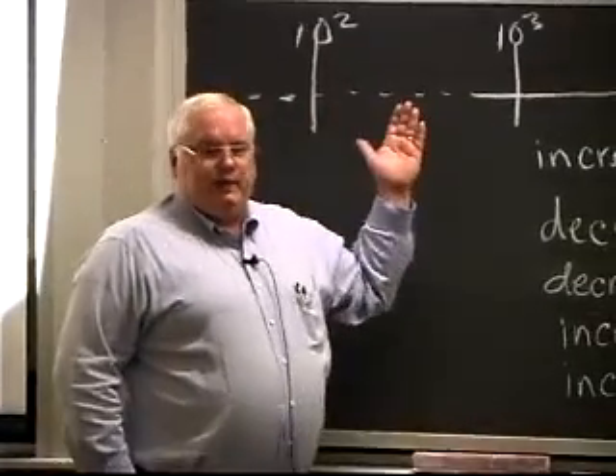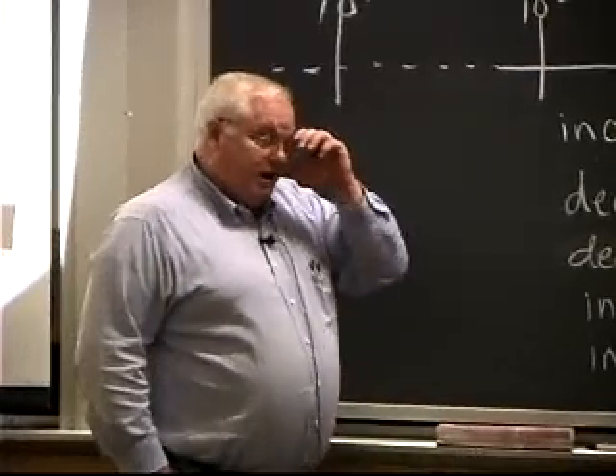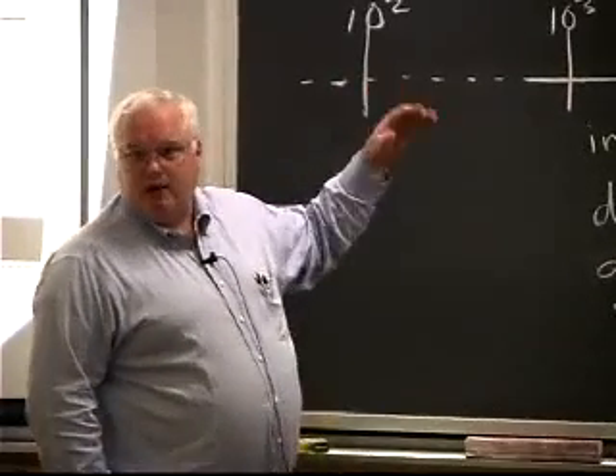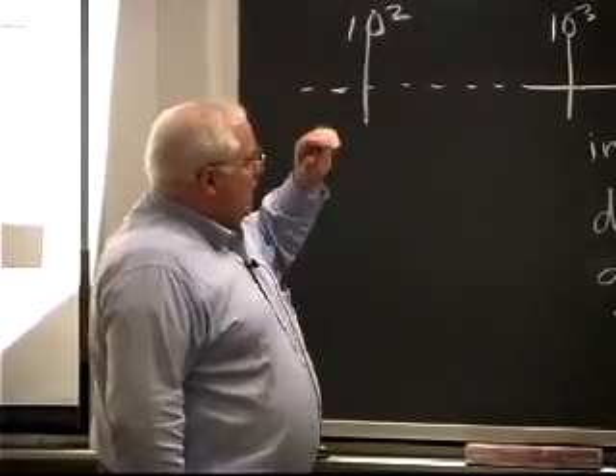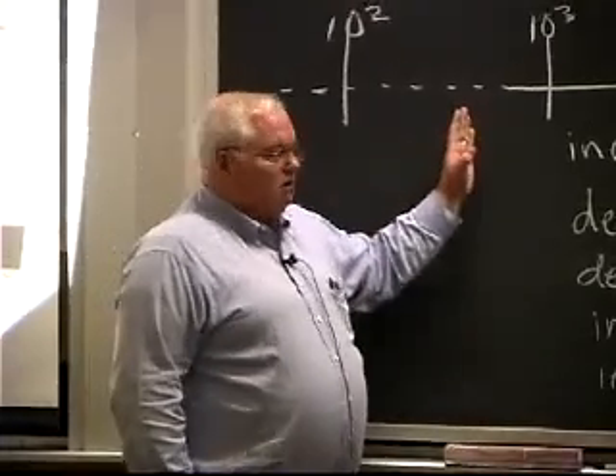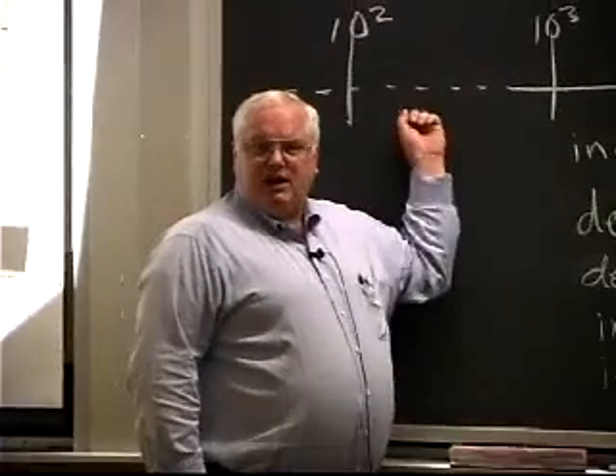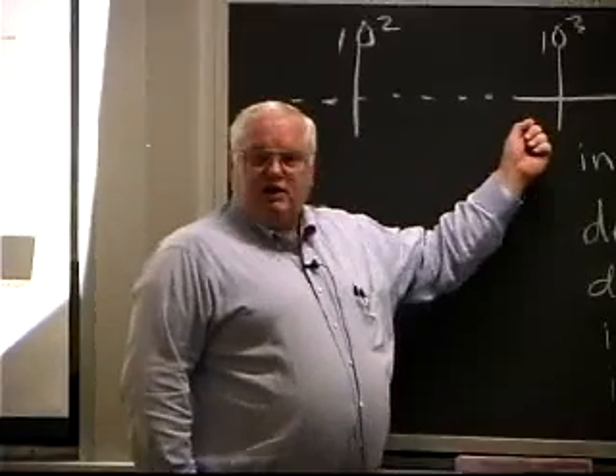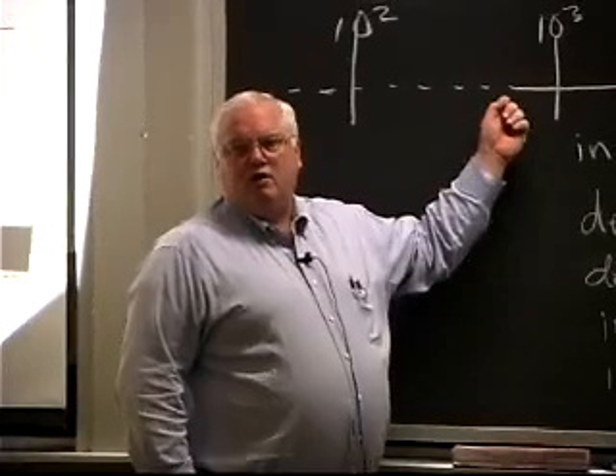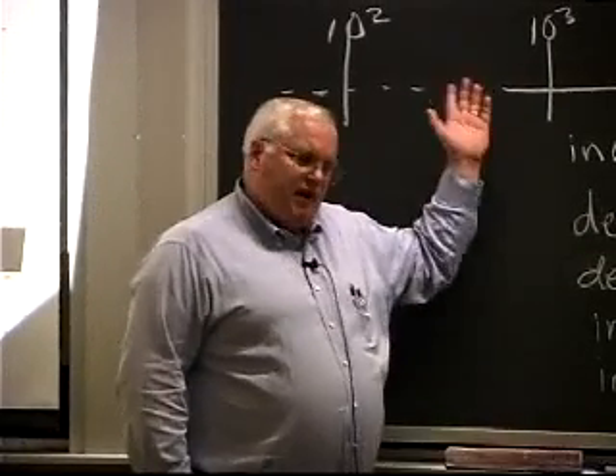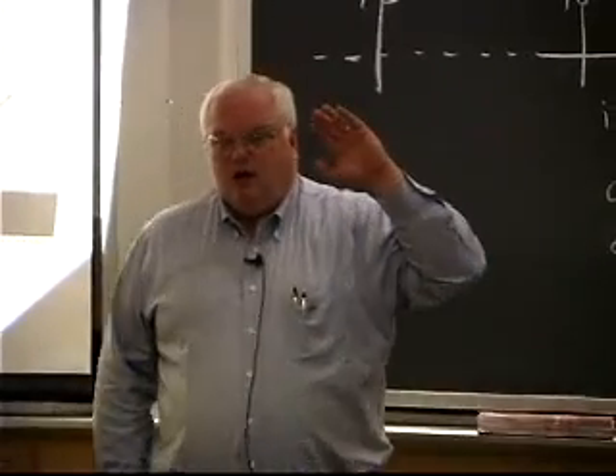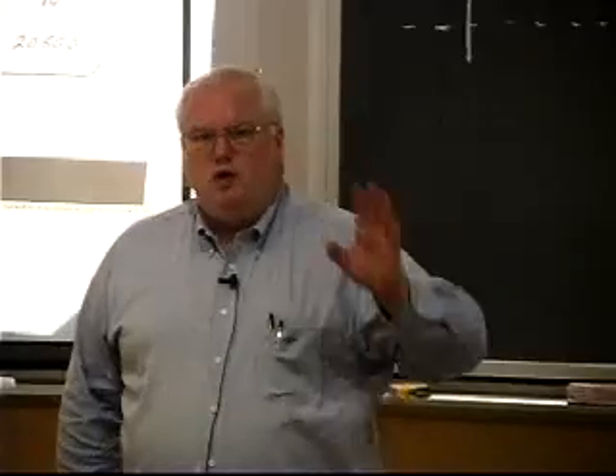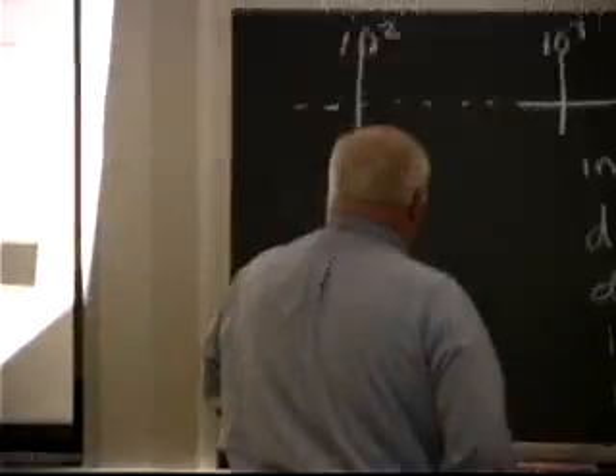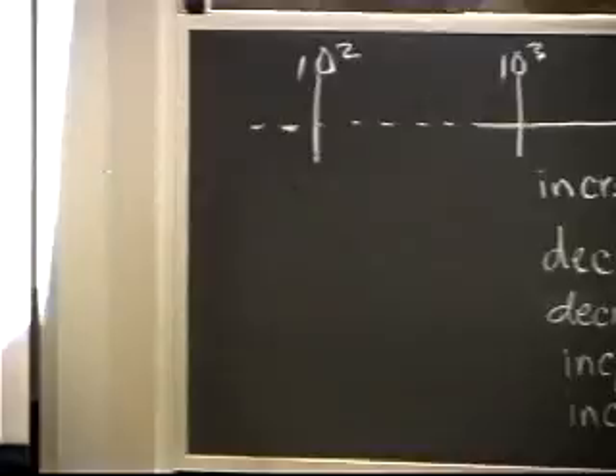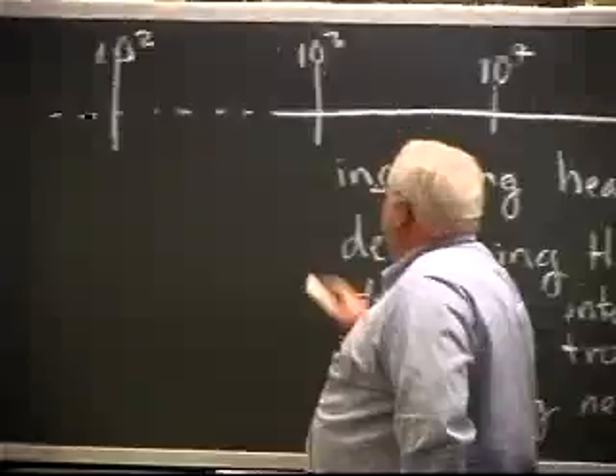Now, obviously, if that was lead, I could have melted lead, right? But if we're talking about most structural metals, iron, aluminum, copper, nickel, or titanium, they conduct heat away fast enough that you've got to put something on the order of 1,000 watts per square centimeter. Maybe it's 500 watts per square centimeter, but it's on the order of magnitude 1,000 watts per square centimeter in order to get melting, okay?